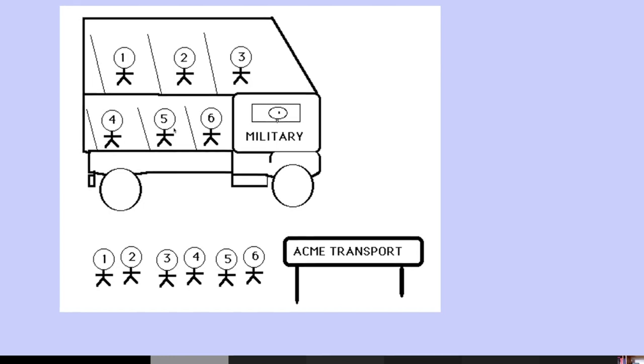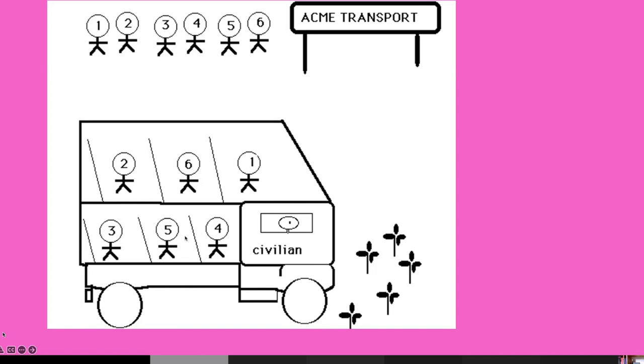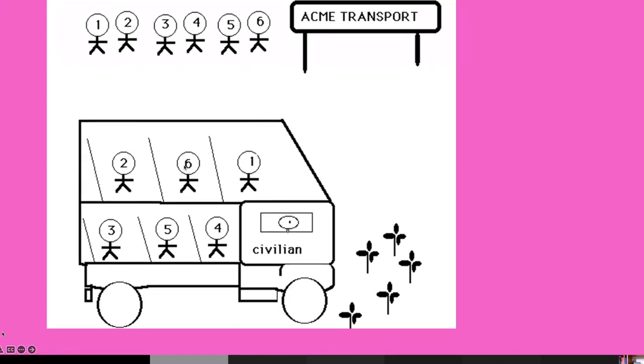Now, if you look at a reconstructive transformation, where we have a queue of civilians waiting at the bus stop, and the bus arrives and they all rush without respect for each other onto the bus, we've lost atomic correspondence completely, and they're sitting next to their friends, and therefore the strain energy here is not as high as with martensite, but we've lost all atomic correspondence. Now, there is a third kind of transformation. So this is a civilian transformation, and this was a military transformation.